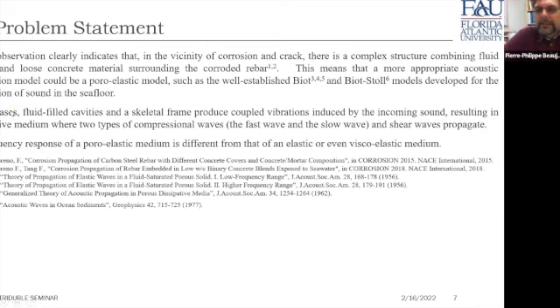In both cases of the Biot and Biot-Stoll model, fluid-filled cavities and the skeletal frame produce coupled vibrations induced by the incoming sound, resulting in a dispersive medium where two types of compressional wave, the fast and slow wave, in addition to shear waves, propagate. So that actually is a more complex and more complete model showing how sound moves and travels through concrete and reinforced concrete in general.